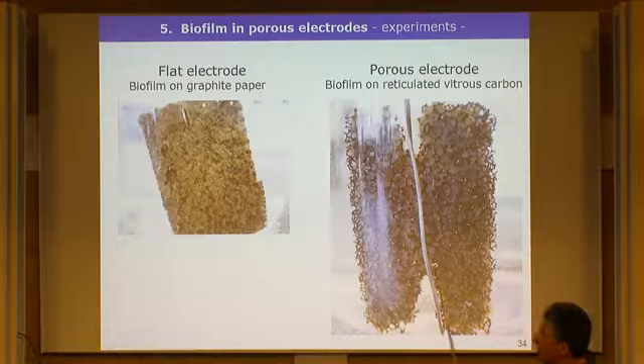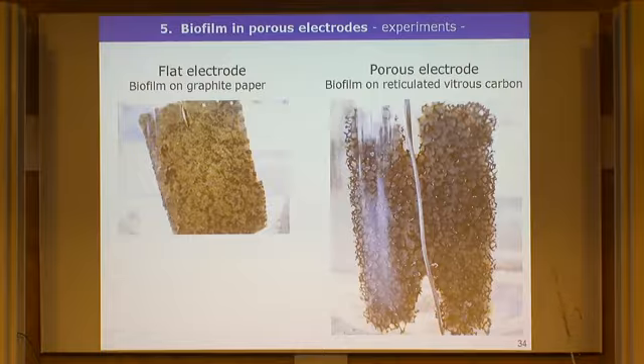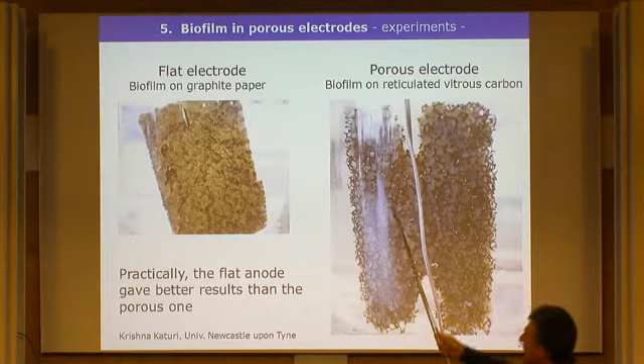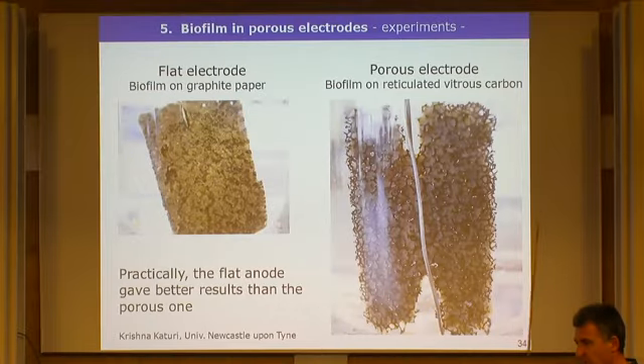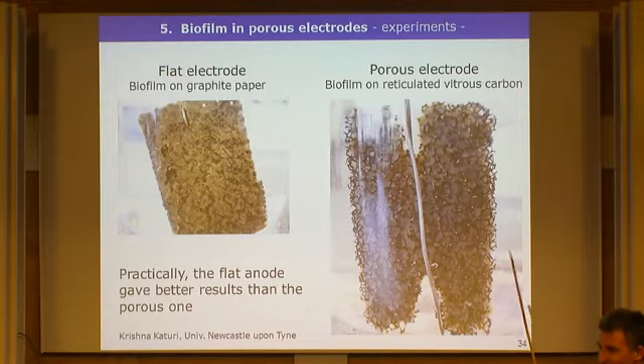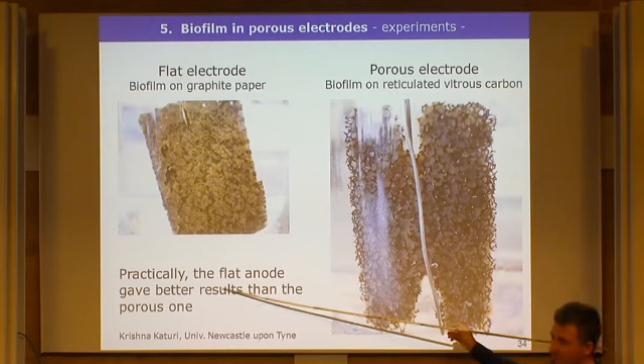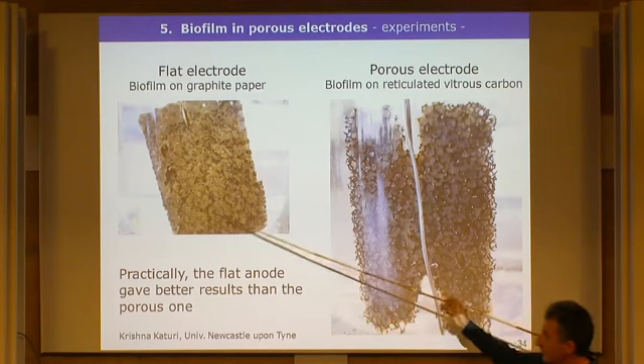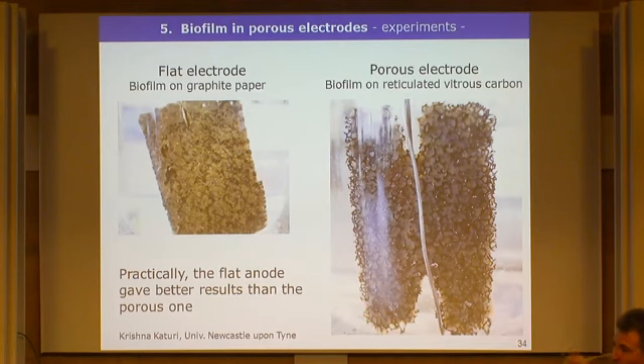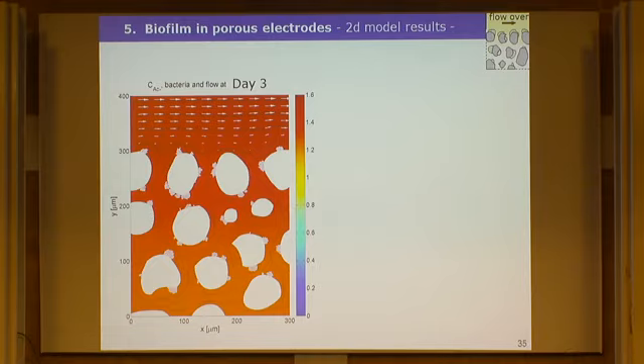This is now the porous electrode. So there were experiments where I did this Marie Curie stage in Newcastle with flat electrodes and porous electrodes. You know, the concept is that the porous electrode should give more surface area per volume. And it should work better, but actually in reality it didn't work better. The flat electrode gave higher currents than the porous one. And the whole point stays here in mass transfer.